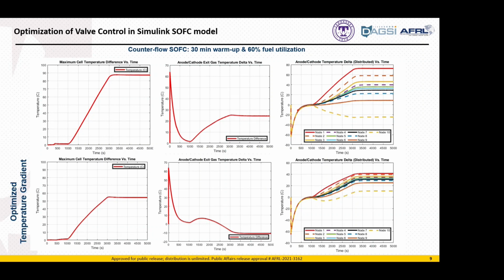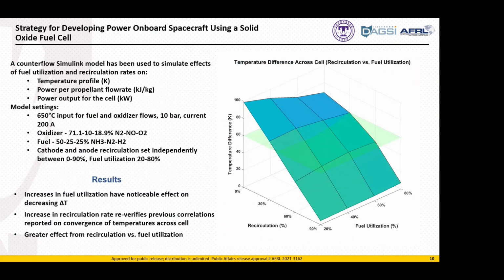And using a MATLAB program that we've developed here, we can interact with the Simulink model and sample different control parameters. And here's a result of one of those efforts where we've tried to minimize the temperature gradient across the cell and minimize the spread of the exit fuel and oxidizer temperature as well. So here we can not only develop an optimized system, but we can have a good idea here at the outset of the control profiles for this system once you would launch it into space.